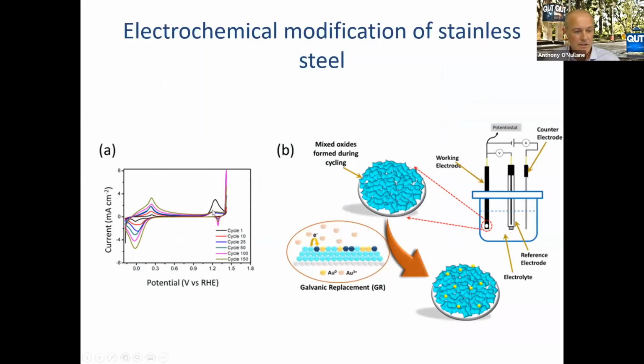So we can see here by electrochemically conditioning our material, here we go up to 150 cycles, that we're getting really good oxygen evolution currents being developed at our catalyst.